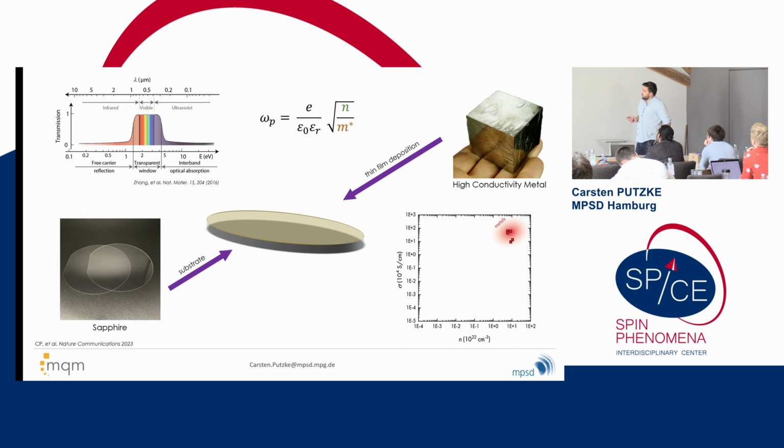Now, one thing that you can do, if you look at what I can actually do to a material in order to make it transparent, is I can play with the carrier density. That's how people use semiconductors and ITO, for example, to tune this and come up with ways for a material to really be transparent at much higher thicknesses, so 100 nanometers or so.